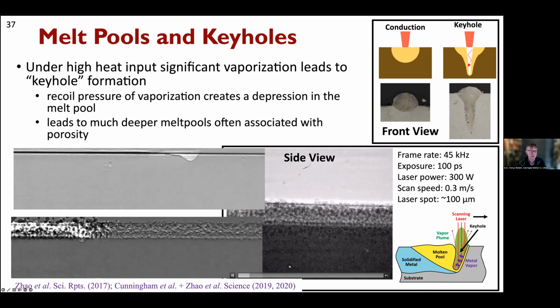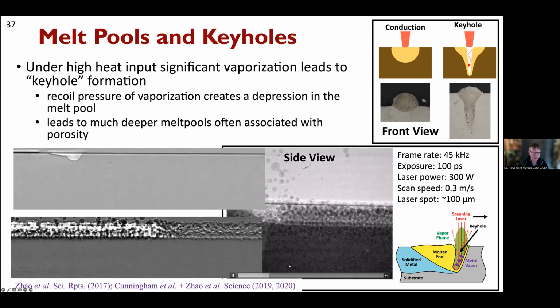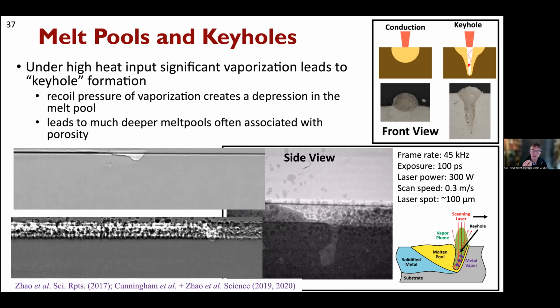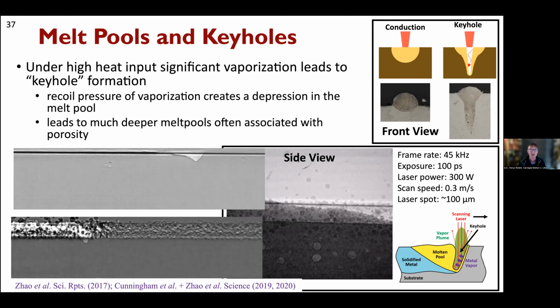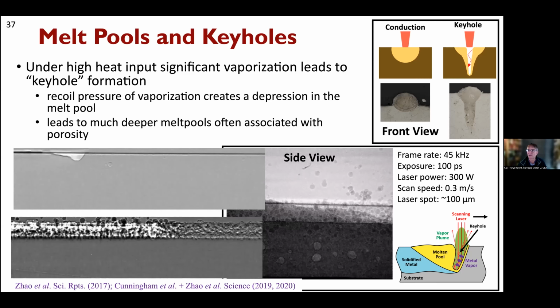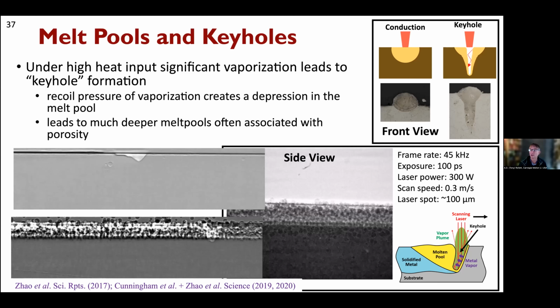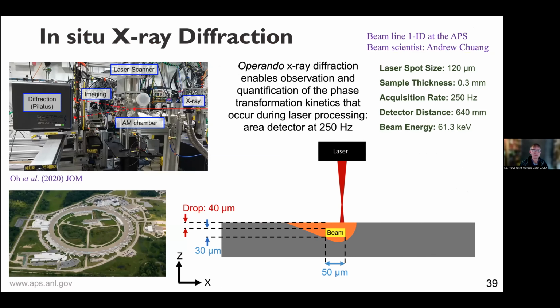So this movie back here does actually show you the thing pinching off at the bottom and leaving behind these pores. And so it's been extremely useful for quantifying defect formation in situ, even operando, if you like. So the typical frame rate there is 50 kilohertz, but you can actually get to 10 megahertz and see lots and lots of detail. So that's fine in terms of visualization, but I think this audience is probably more interested in a more detailed view of what's going on.